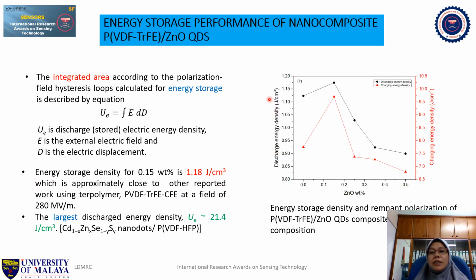The discharge energy density and also charging energy density with respect to the zinc oxide weight percentage is shown in this figure here. So it is actually calculated from the integrated area of the polarization hysteresis loop, as we discussed in the previous slide. By using this formula, then we can calculate the energy storage.